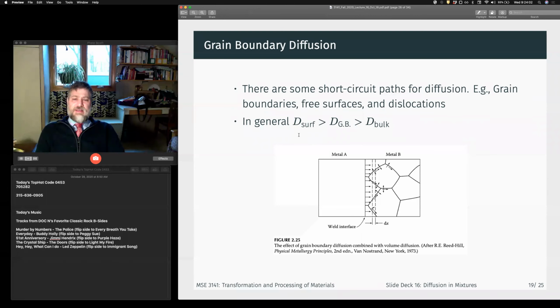So the diffusivity tells you how fast something can move along a certain path, but it doesn't tell you anything about how much that path actually accommodates, right? So if I have a big sample, the amount of atoms on the surface relative to the volume is very small. And the same thing if I have large grains, the amount of grain boundary area relative to the bulk of my grain is also very small. But if we look at diffusion in polycrystal samples, a lot of times you see that there's a faster diffusion on the grain boundary than there is through the bulk, right?